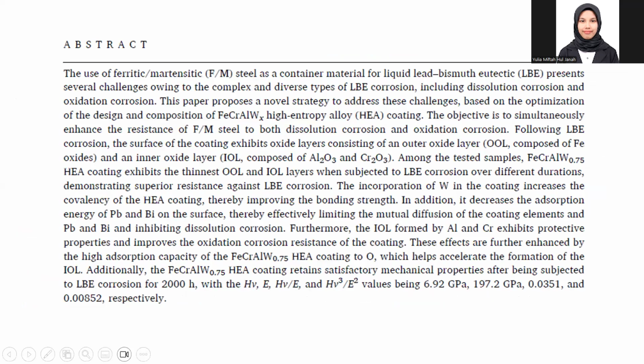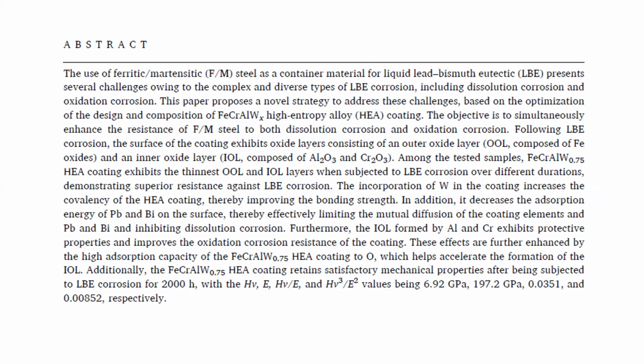Okay, about the abstract. The use of ferritic-martensitic steel as a container material for liquid lead-bismuth eutectic (LBE) presents several challenges owing to the complex and diverse types of LBE corrosion, including dissolution corrosion and oxidation corrosion. This paper proposes a novel strategy to address this challenge based on a FeCrAlW high entropy alloy (HEA) coating. The objective is to simultaneously enhance the resistance of FM steel to both dissolution corrosion and oxidation corrosion.